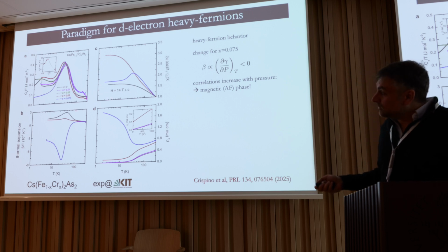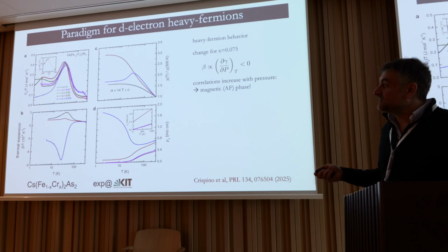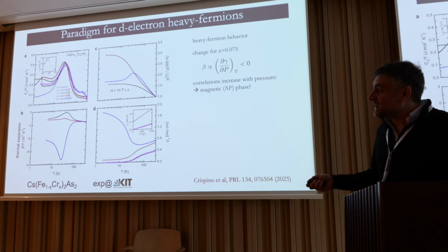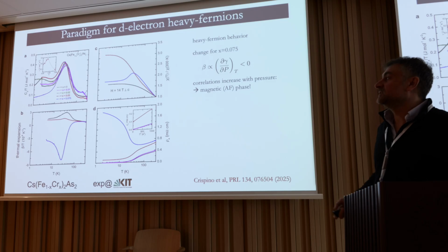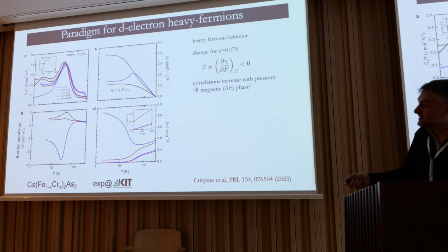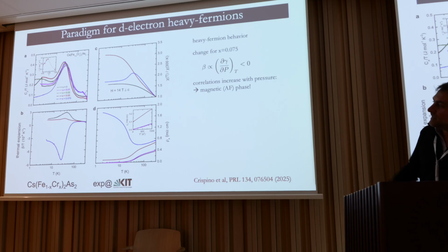And they also, in Karlsruhe, like to look at the thermal expansion coefficient, which is very interesting because it's positive for all these compounds with high Sommerfeld coefficient, and it all of a sudden becomes negative for this compound with 7.5%. And also the resistivity goes from metallic to semiconducting insulating.